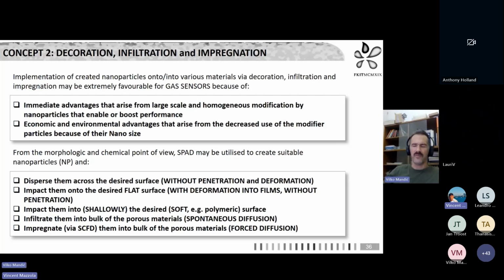So how do we play with that? We can utilize the method to disperse them across the desired surface without any deformation and penetration. Then we can really impact them and make real films of the material that we're depositing, without deformation in the films. So basically make thin films, but without penetration, because we use a material that is not soft, so basically a hard material. If we use soft materials, we can penetrate into them and make a shallow layer of modified properties, and normally that would be a polymeric material.